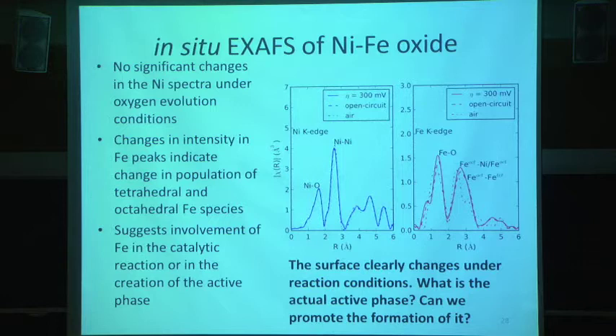Now, if we go and look at XAFS, we can do this actually under electrochemical control. So we can take a sample in air, then we can put electrolyte in at open circuit, and then we can apply an oxygen evolution overpotential, and we can look for changes in the activity of the surface. And we don't really see anything in the nickel edge. We see no change in the nickel-oxygen edge, almost no change in the nickel-nickel XAFS shell. But over here in the iron shell, we see a lot of very different changes. So these peaks right here and these peaks right here change in their relative amounts. And these are the peaks associated with octahedral and tetrahedral-octahedral coupling. And so what we're seeing is that the speciation of iron is changing under the reaction conditions. We're getting changes in the population of tetrahedral and octahedral sites that exist in the iron nickel spinel. And the surface is clearly changing under the reaction conditions.